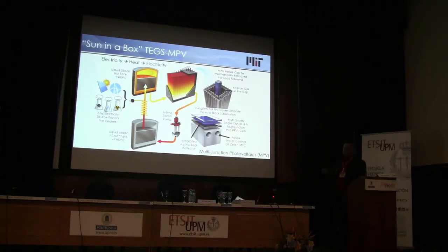We just take the convective heat leakage hit on the efficiency. One of the other reasons that it's good to go to very, very high temperatures is we can get the PV output to outrun all these other losses. So the PV output, the amount of light that you have coming out of this infrastructure, is scaling with T to the 4th. And so as you go hotter and hotter, you quickly overcome all the other sources of heat leakage. You've got heat leakage out of the system through this insulation. You've got heat leakage through convection across the gap, and so you're able to outrun these. These losses still exist, but those losses scale linearly with the increase in temperature, but the radiation scales with T to the 4th, and so you're able to get to a temperature range where you win.